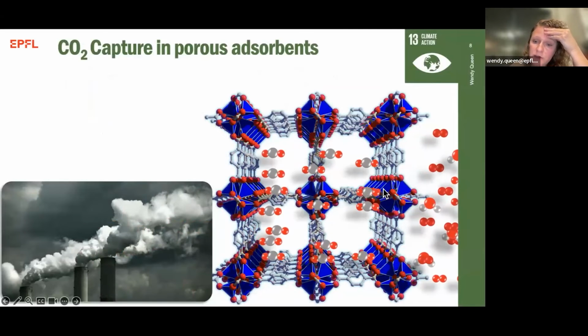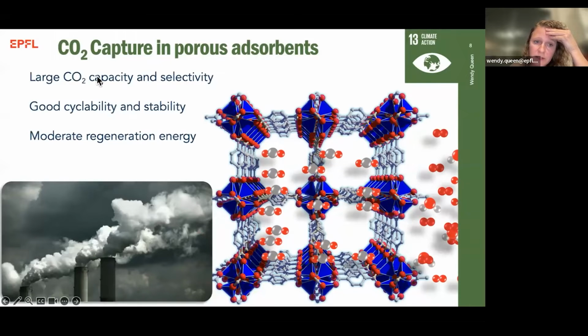So from there, our goal is really to design materials that, when we have a gas mixture, can grab that CO2 and allow the other small molecules to pass through the material. So our goals initially really are to design a material with a relatively high CO2 capacity, so it absorbs a lot. It's selective for CO2, particularly over nitrogen, which is the main component in post-combustion flue gas. We want a material that can not only absorb CO2, but also release that CO2. And we want it to do this over a long, extended period of time. The reason that we want that, of course, is because we don't want to have to replace our adsorbent every few months. Of course, we would also like to have a moderate regeneration energy because this basically reduces the energy input that's required for our entire process.